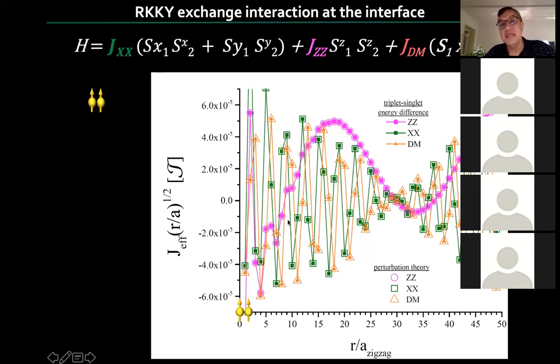So you can see that this purple one here, the ZZ, is the one that dominates as far as amplitude, and it has the lowest oscillations, while the other two, the in-plane and the Dzyaloshinskii-Moriya, have a much higher frequency. The reason for that is that the sectors of the Fermi surface that are involved in the scattering are different. And so they have different frequencies as a consequence. They have different Fermi frequencies. But what is interesting is that all three interactions are, as far as amplitude, very, very similar.